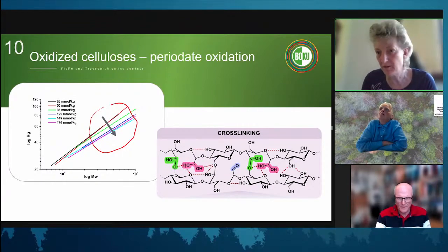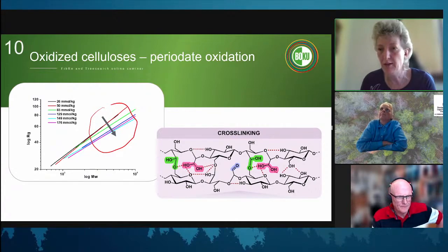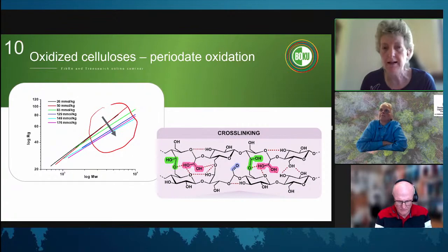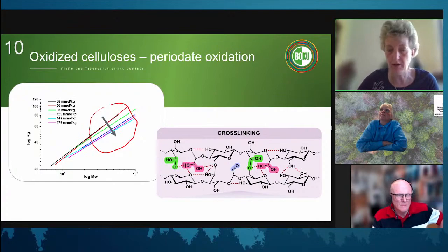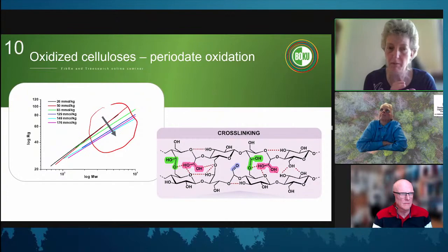At the edges you always have a lot of deviation, and it depends a little bit on the scattering quality you have. For instance, we are running celluloses only with 488 nanometers, with a blue laser, because the scattering is better in that range. The dn/dc is larger and so on. But you have to cut away the high molar mass because their scattering is nice, but the concentration is low, so RI is not a very good detector. On the low molar mass side, it's the other way around. The scattering is bad, even though your concentration is still acceptable.